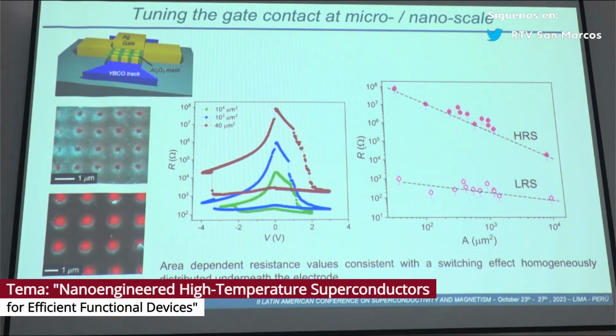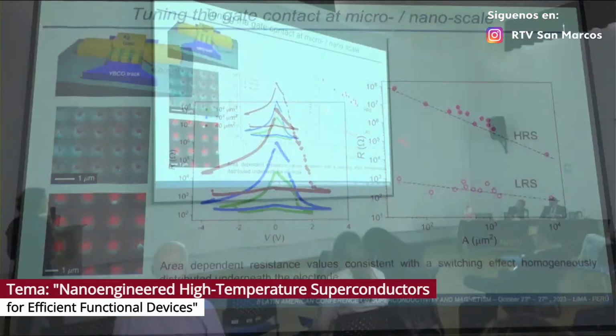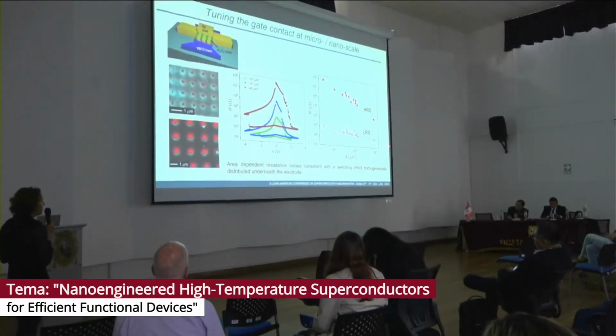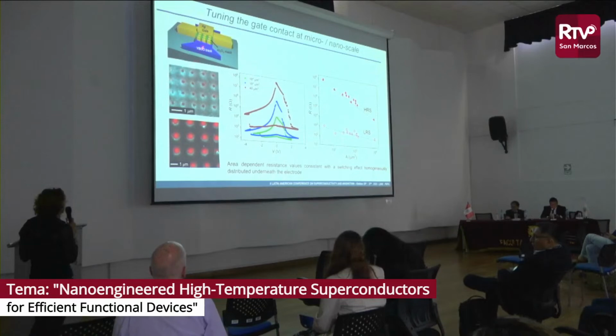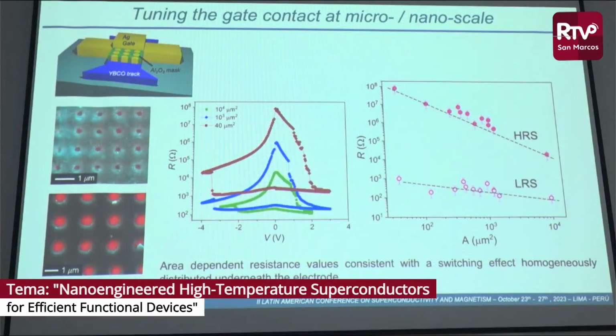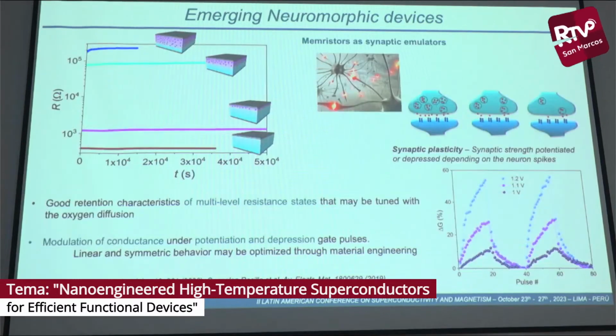And by changing the structure of the gate, which would be the electrode where we apply the voltage pulse, we can change the level of the low resistance state and the high resistance state, which scales with the area of the device. And this means that we have a consistent transition below the gate, and we have a consistent change of the oxygen doping inside the gate. In this case, for example, these systems could be used in order to design memristors for neuromorphic devices.